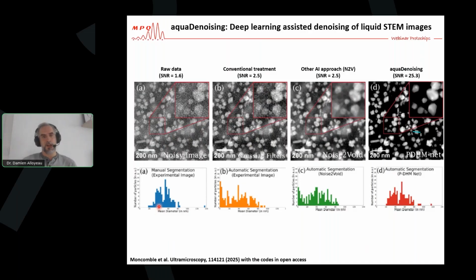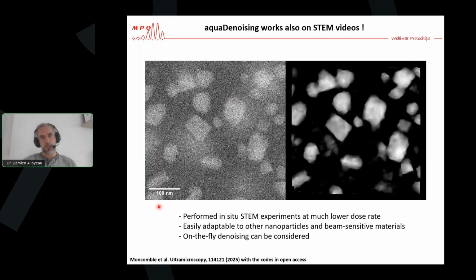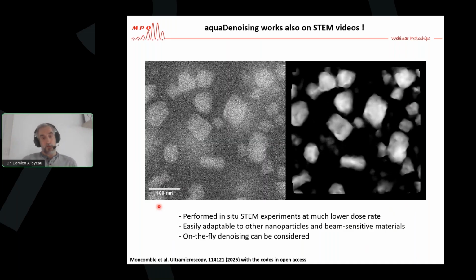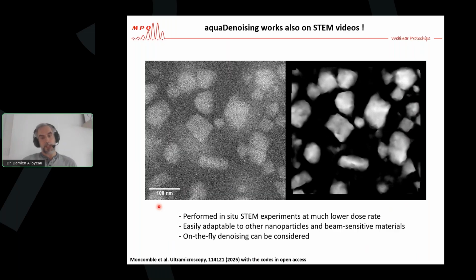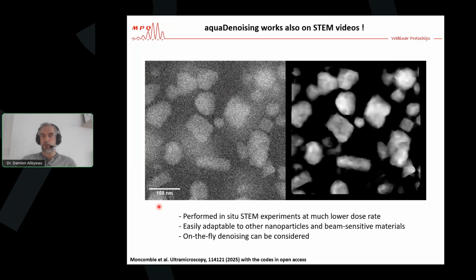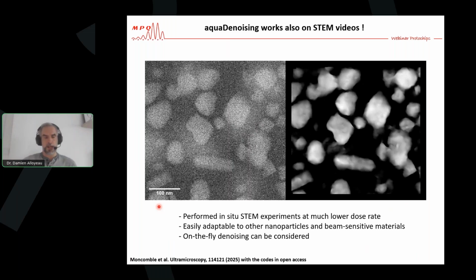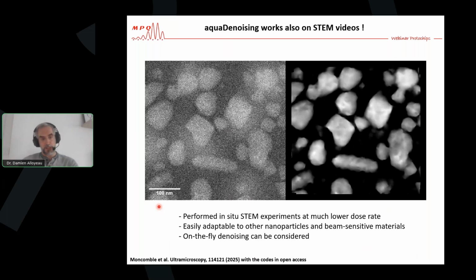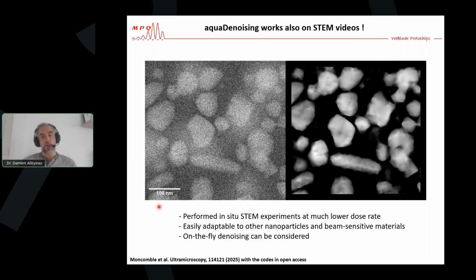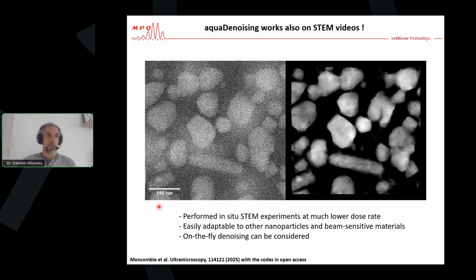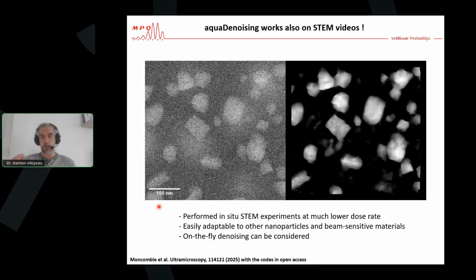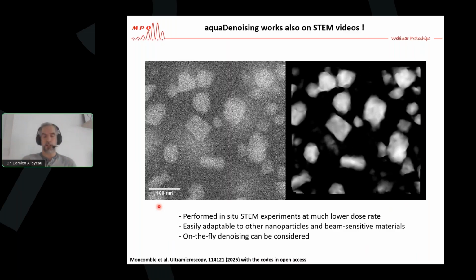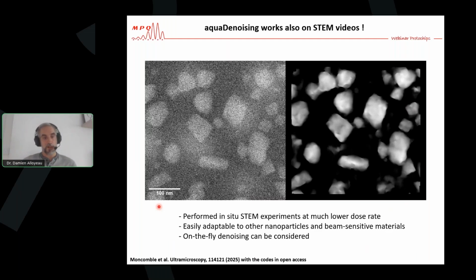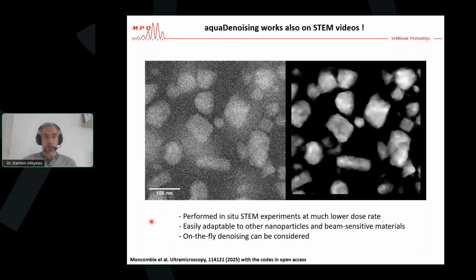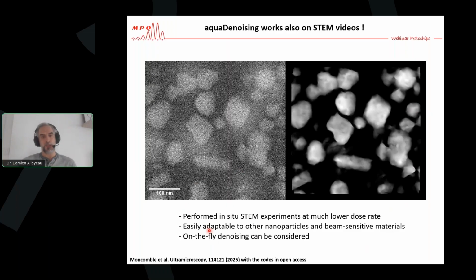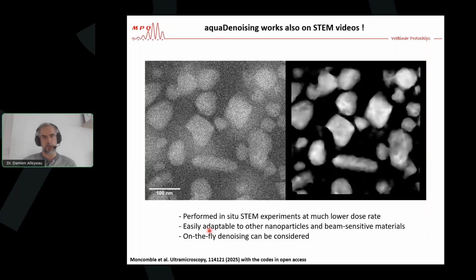So what are the main advantages of these new methods? We will be able to perform in situ STEM experiments at much lower dose rate and recover the loss of signal-to-noise ratio with the AI approach. Most importantly, this approach can be easily adapted to other materials and beam-sensitive materials. It takes only a few hours to train the networks. Again, what you have to take into account is the composition and the variety of size and shape that you have in your liquid cell. And those treatments are extremely fast, so on-the-fly denoising can be considered. That's what we are working on now.